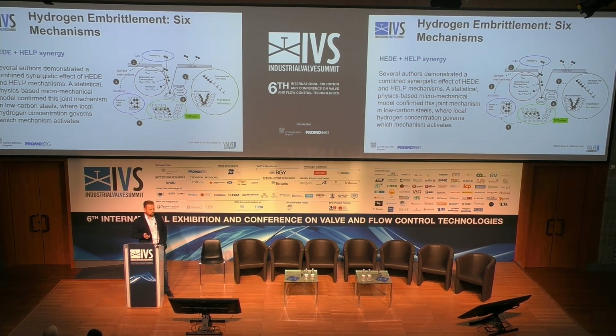After that, we observed also some combinations. So, for example, HEDE and HELP synergy, it's something that is well documented in literature, and right now, once we started using more and more hydrogen in the energy mix, this kind of combinational effect is something that a lot of academic papers, but also companies are starting to invest in, because they notice that, like we said before, it's not black or white. You need to think and understand that everything that happens on top of your material, on top of metal, impacts strongly how hydrogen is going to interact with it.